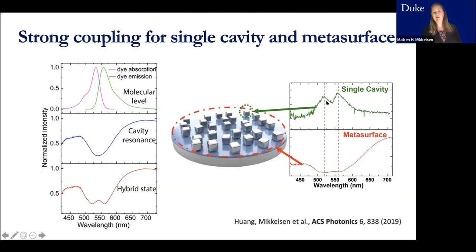You can notice here for a single cavity, to measure the plasmon resonance in this hybrid state, we're using white light scattering. So we are seeing it as peaks. But for the metasurface, we're doing it in reflectance. So we're seeing it as a dip. But it's really both indicating the plasmon resonance in this hybrid state. And we also did check if we could bleach the dyes and if this double peak would go away. And it indeed did. So that was a nice check.